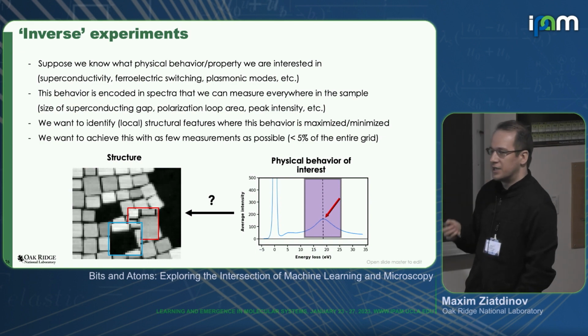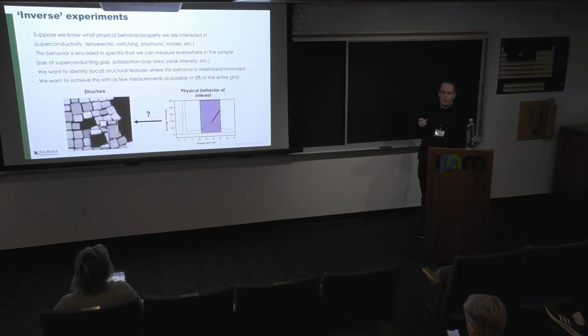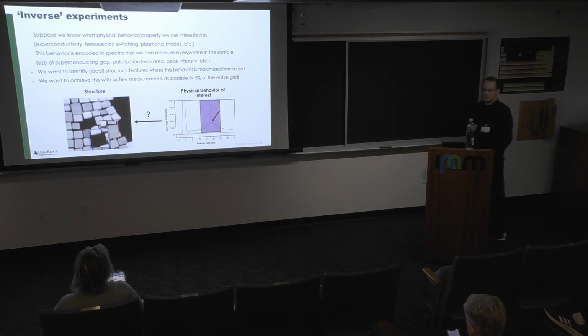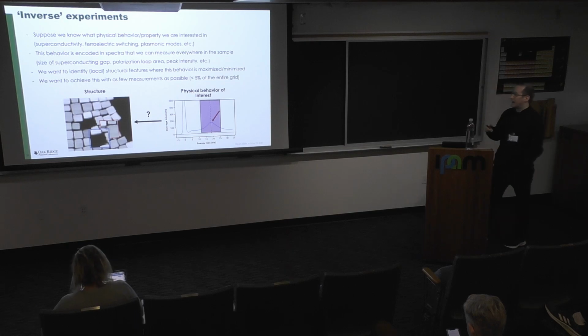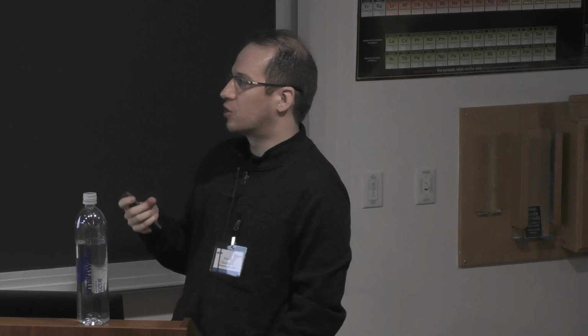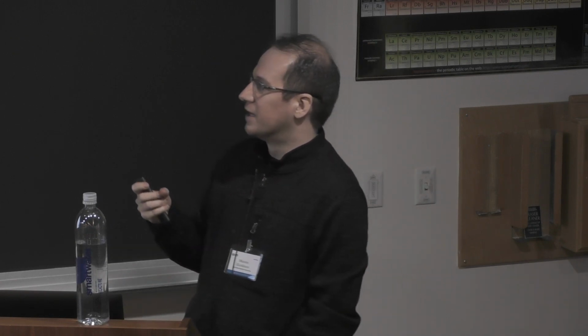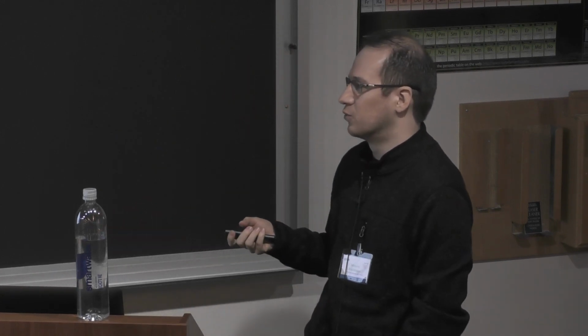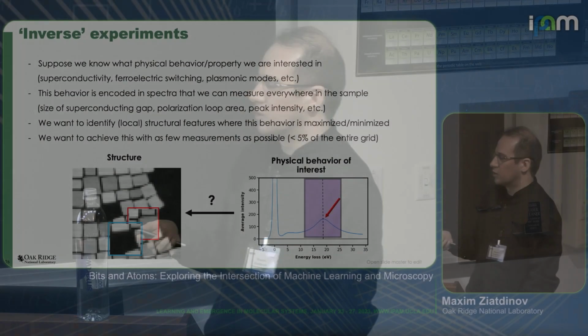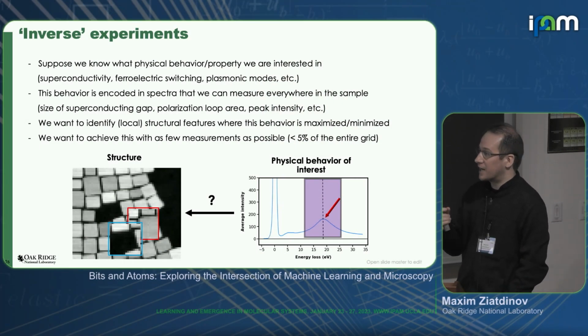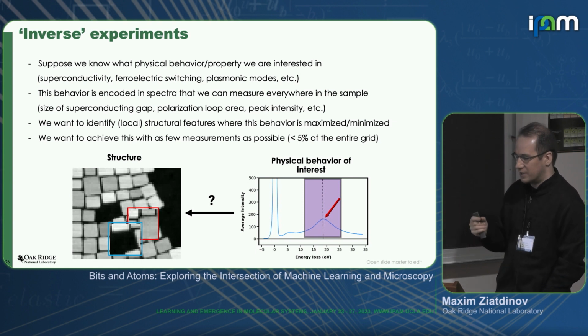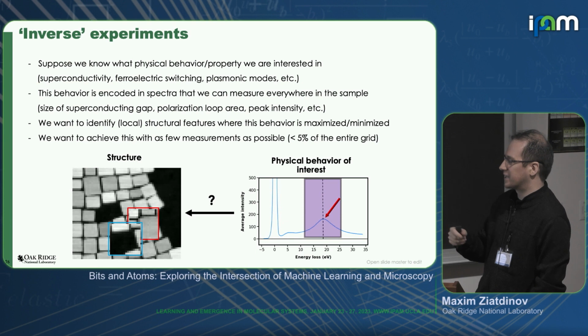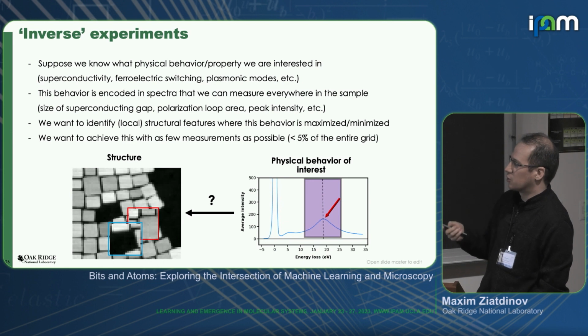And the idea here is that in many cases, we already know what physics we are interested in, like superconductivity, ferroelectric switching, studying plasmonic modes, and so on. And we also know that this behavior is typically encoded in spectroscopic data that we can measure in principle anywhere in the sample, right? It could be something like size of the superconducting gap, polarization loop area, peak intensities, and so on. And what we don't know is what type of structures produce that behavior, right? We have some idea from theory, but it frequently breaks down in real materials. So we want to learn what type of structures host that behavior.